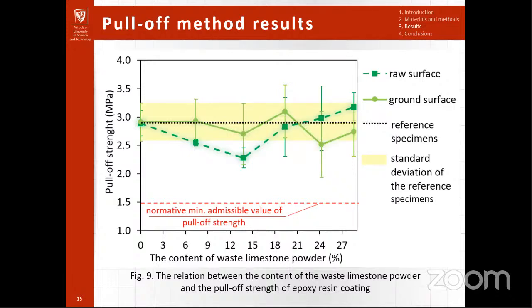In Figure 9, we presented the obtained values in the form of a graph of the relation between the content of the waste limestone powder and the pull-off strength of coating. The control samples of both types of surface obtained almost the same results, about 2.9 megapascals. The pull-off strength results for all samples are above the normative minimum pull-off strength value. All average pull-off strength values are between 2.3 and 3.2 megapascals, which shows that the addition of waste limestone powder generally did not deteriorate the pull-off strength of the epoxy resin coating.